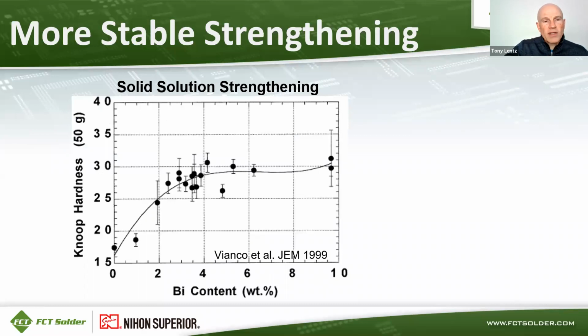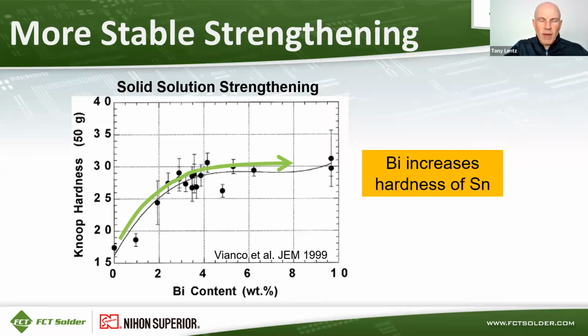Here's the Knoop hardness of tin bismuth mixtures. Bismuth increases from left to right on the x-axis. You can see that as bismuth increases, the hardness increases pretty dramatically, but then it plateaus between about, say, 3.5% and 9%. Bismuth definitely increases the hardness of tin, which could be considered a good strengthening effect.